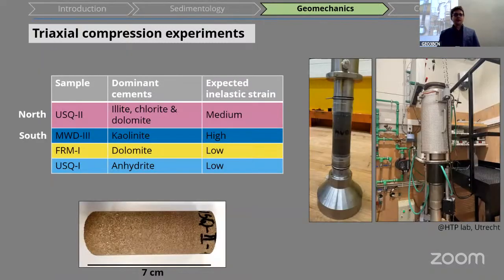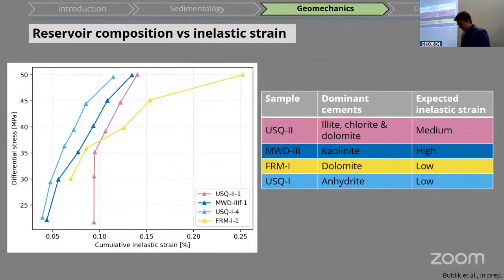So what we do is we take these samples, put them into a triaxial deformation apparatus, which was done at the University of Utrecht. And based on the composition of these samples, we would expect that they behave differently if we compact them. So you can see here, for these clays, we would expect that they compact relatively large, while if we have very strongly cemented samples, we would expect that they deform relatively low. So let's see what we actually get.